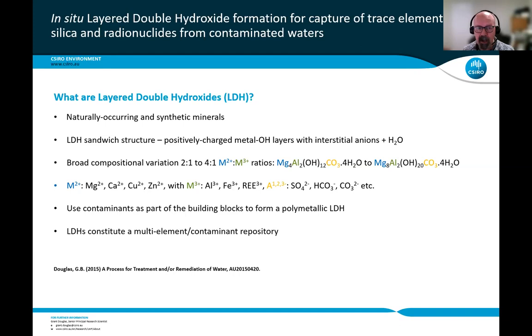Luckily, there's a broad compositional range for layered double hydroxides. So you'll have anything from say a 2:1 to 4:1 M2+, a metal 2+ to metal 3+ ratio. And there's a couple of formulas there. The first one being a 2:1, where you've got Mg4 to Al2, and then Mg8 to Al2 is your 4:1 ratio. Now, a really fortuitous characteristic of layered double hydroxides is that you're able to substitute a whole range of metals into them. So for the M2+, you've got your typical suspects there, so magnesium, calcium, copper, zinc, and a whole range of others. And for your M3+, your Al, iron, rare earth elements, again, a whole lot of others. And for your anions, you can have monovalent, divalent, trivalent anions, and again, things like sulfate, bicarbonate, carbonate, and the like.